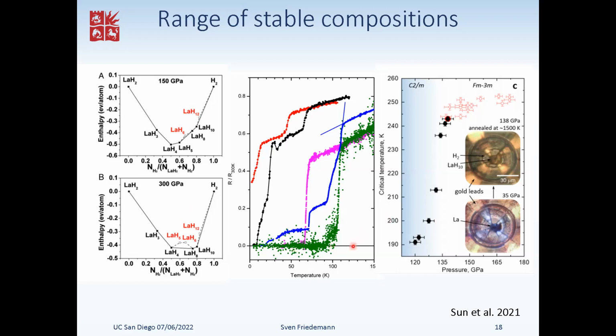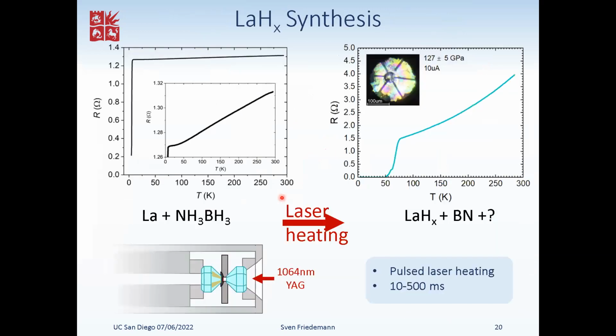In resistance, you get not just the transition that I showed on the previous slide at 250 Kelvin, but you also get transitions in some samples at 100 Kelvin or 60 Kelvin or even 20 Kelvin only. And the resources have not been invested to really disentangle this. We've worked a little bit on this ourselves. We see that we can also form what you might call lower hydrides, because it's not the full highest TC. For instance, if we react lanthanum with ammonia borane, we get some curves that have a resistive transition at about 70 Kelvin in some of our samples.